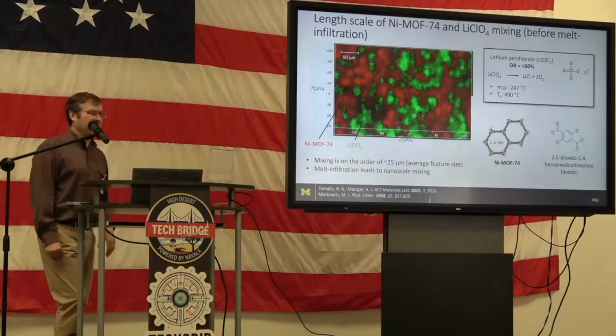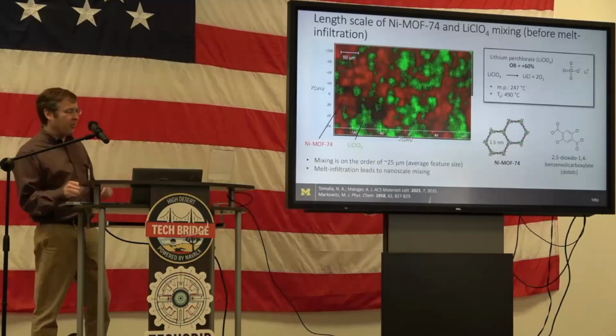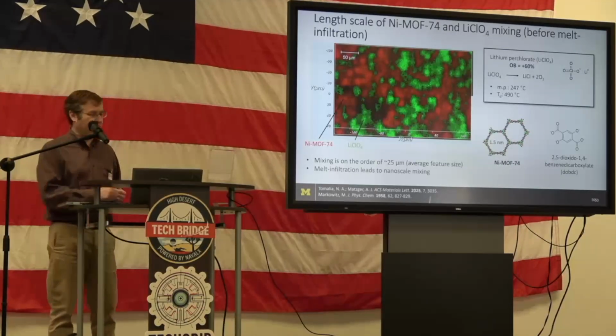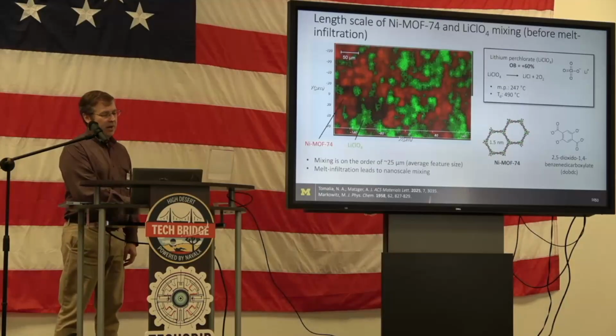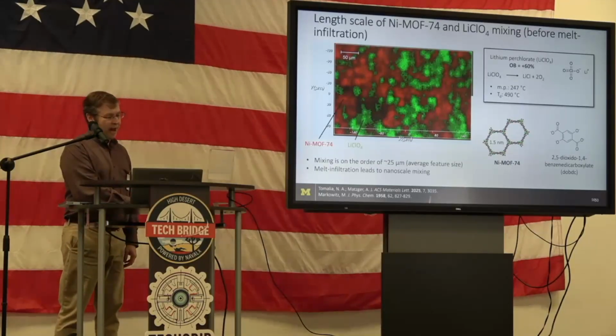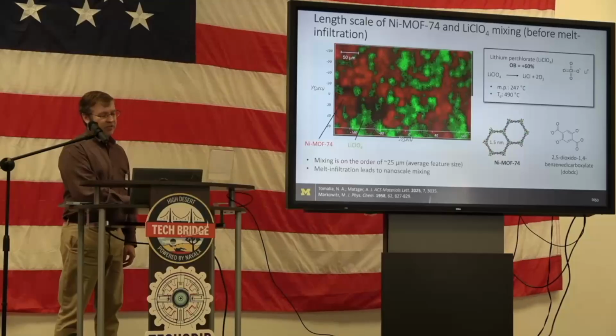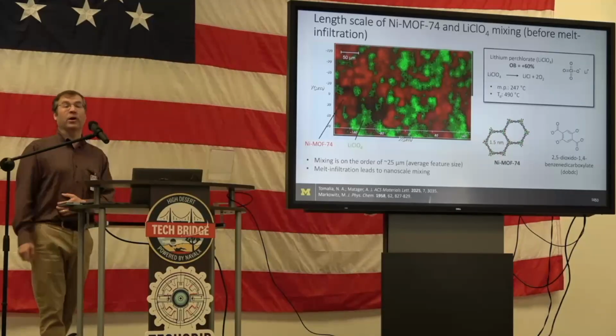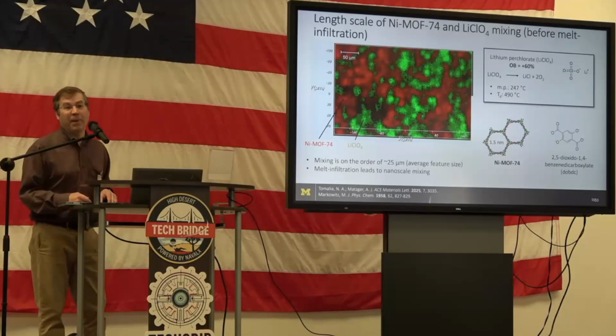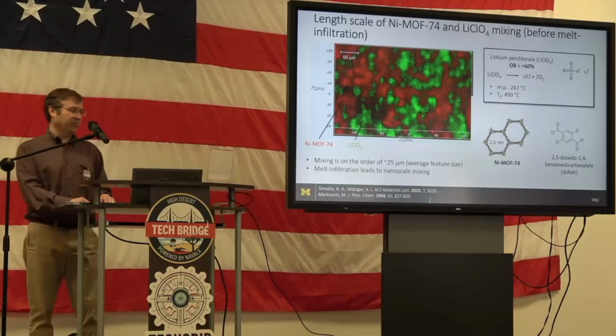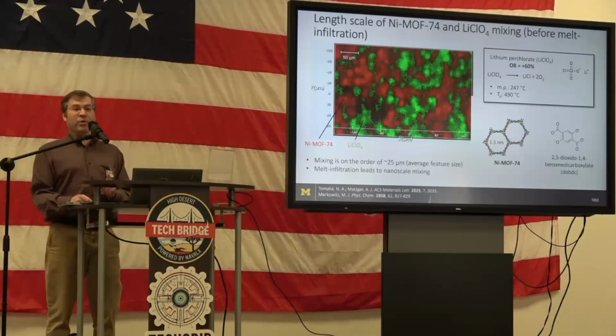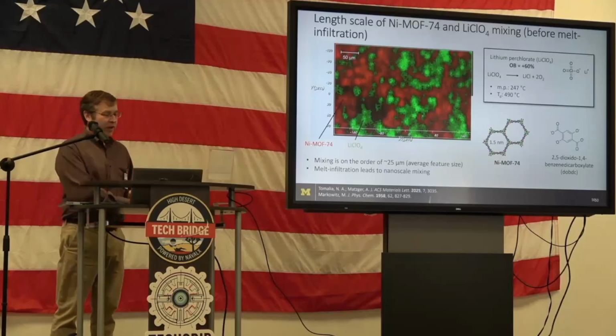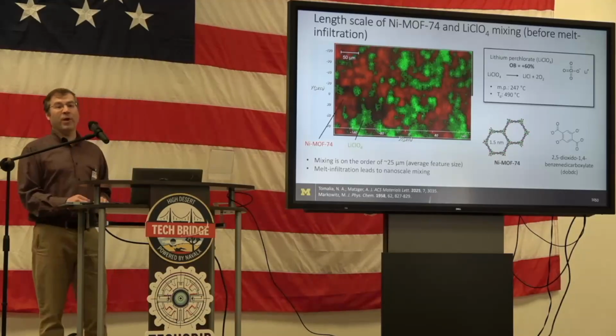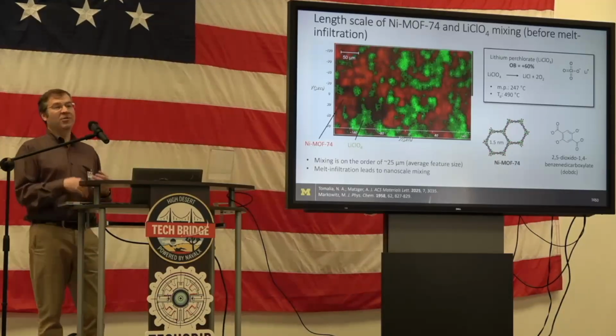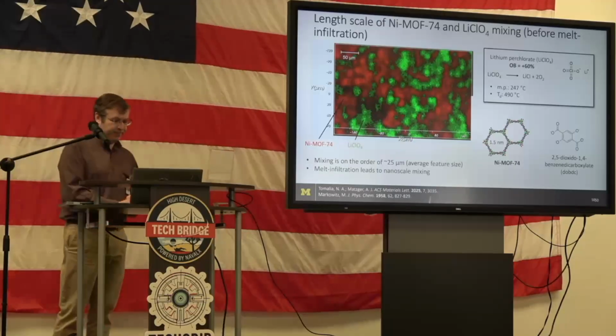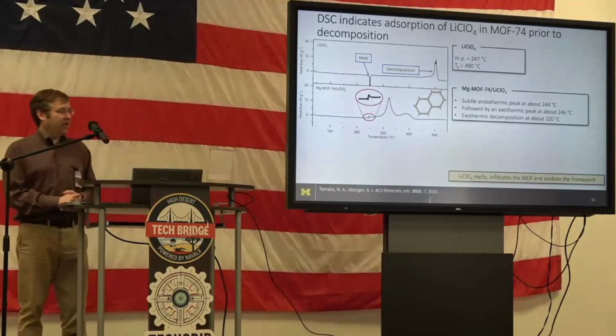So here's what this looks like. This is a Raman spectroscopy map of the physical mixture of the MOF, which is in red, and the green oxidizer. And this actually looks very similar to a composite propellant in terms of the length scales of mixing. But now we're going to melt it so that all the green stuff gets sucked up by the red stuff and now becomes mixed at the nanometer level.